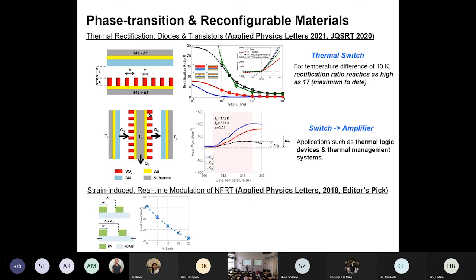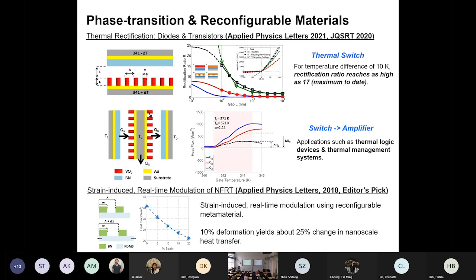So if we're able to design and fabricate our metal surface pattern on top of a soft, reconfigurable, stretchable material substrate, this material actually can be reconfigured. So the material we chose here, bottom is the PDMS, clearly softer material, and we deposit our boron nitride on top. It's still common. Okay, just give this concept here. So under mechanical deformation, you clearly see the period of the grating of the surface elongated, and we demonstrated this one. This can be pretty fast.